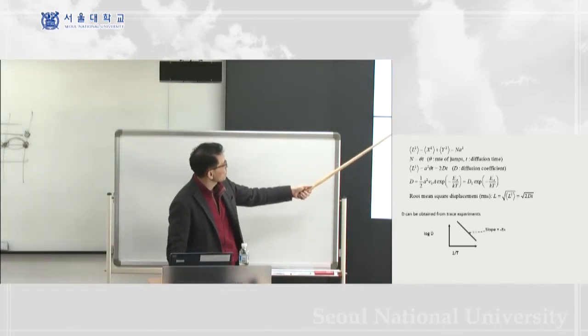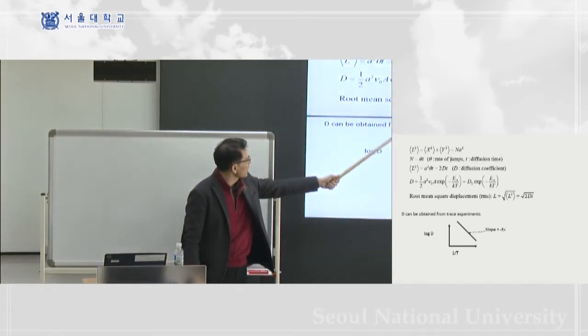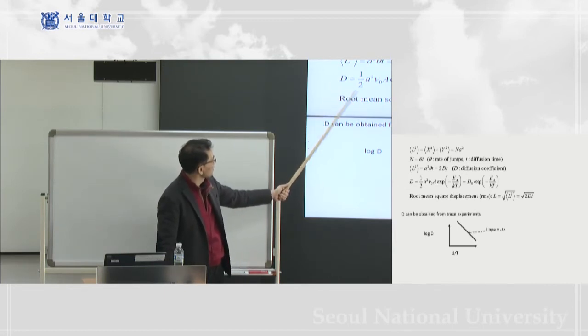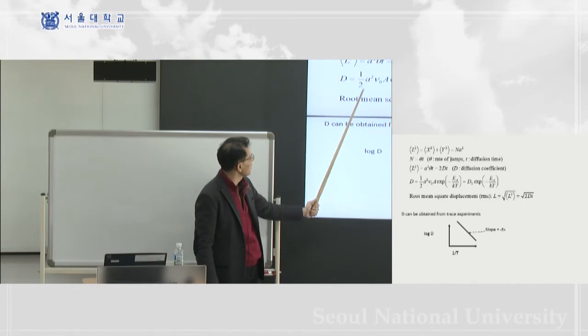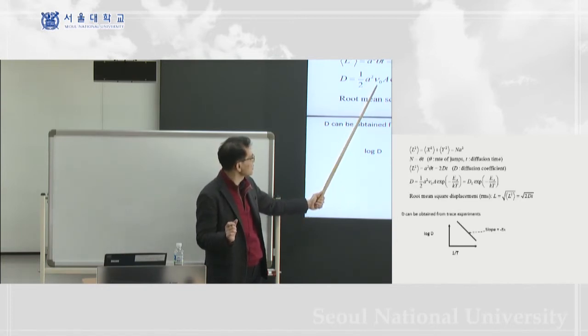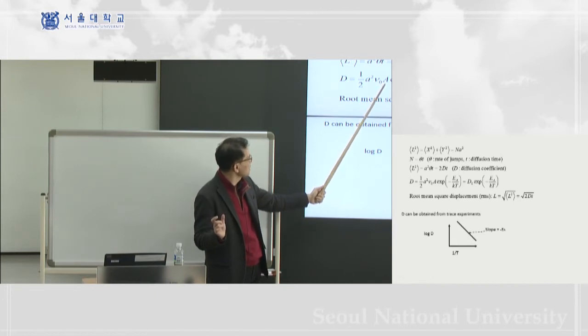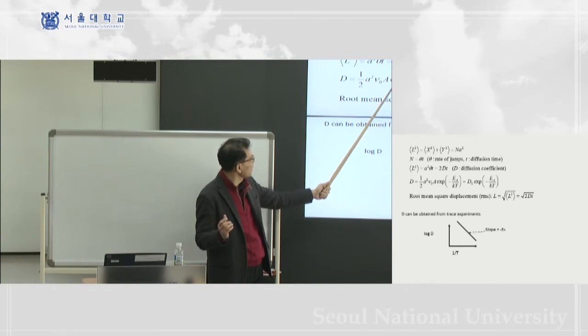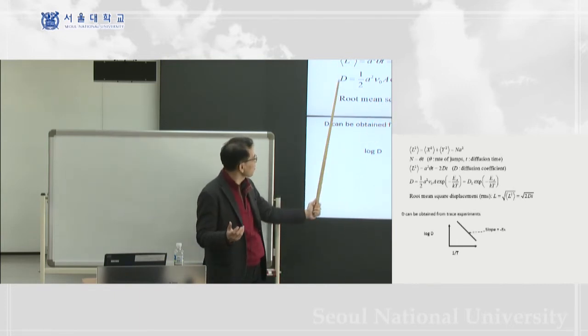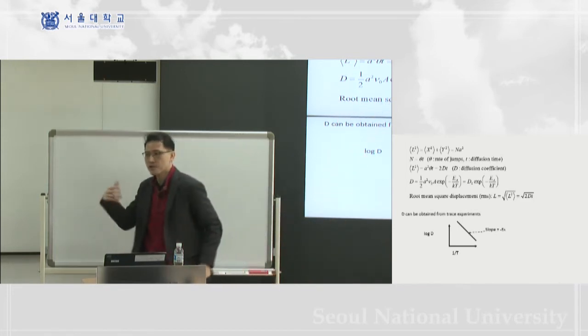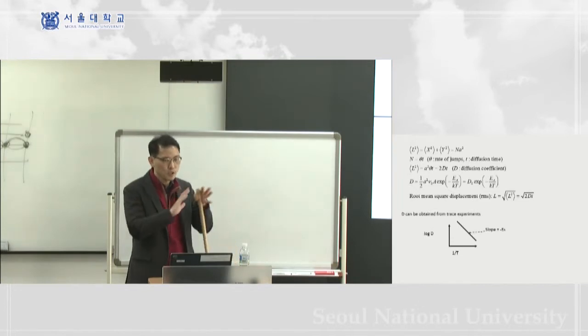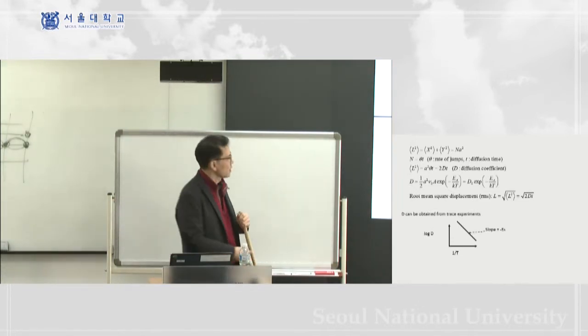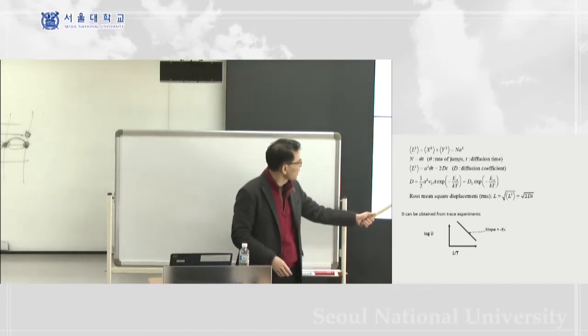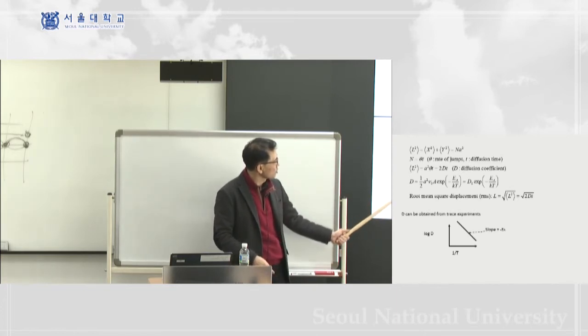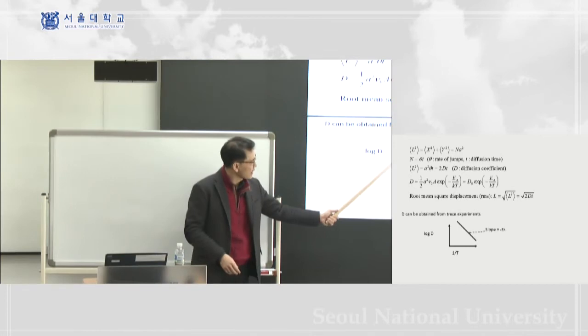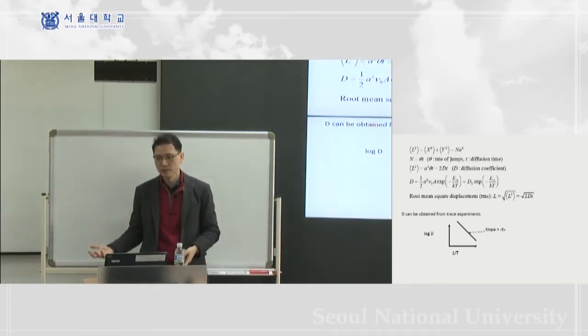And this root mean square displacement is now proportional to square root of 2Dt, and so you can obtain the diffusion coefficient from this expression, where a is the lattice parameter, and nu naught is the phonon frequency. A is a certain constant, a correlation constant, which is well known, and the activation energy you can obtain from the simulation. So every quantity here you can obtain from the atomistic simulation. All right, so you can completely exclude empiricism in your simulation. And because of this exponential nature, if you plot the log of the diffusion coefficient against 1/T, then you can obtain the activation energy, and you can compare with the experiment.